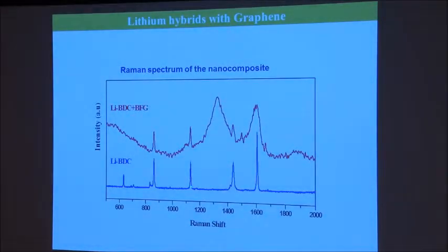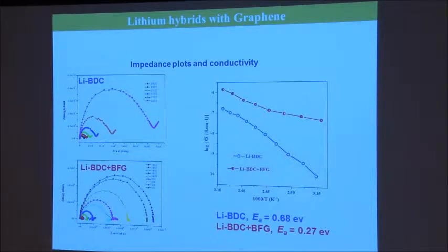Raman bands show the metal organic framework. Such composites have very interesting properties. For example, the lithium ion conductivity in these graphene composites with the lithium metal organic framework is much higher, and the activation energy comes down. This kind of study we are conducting.